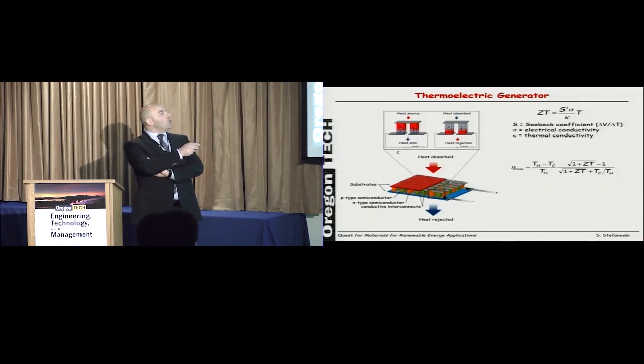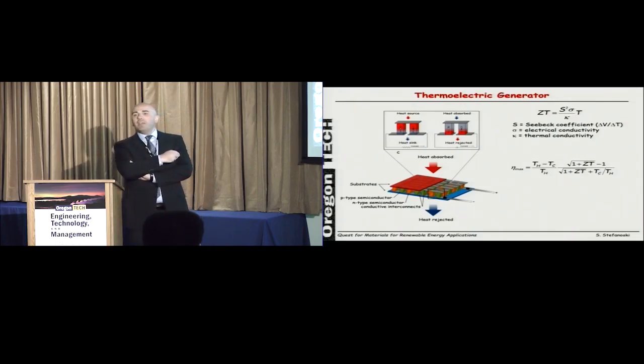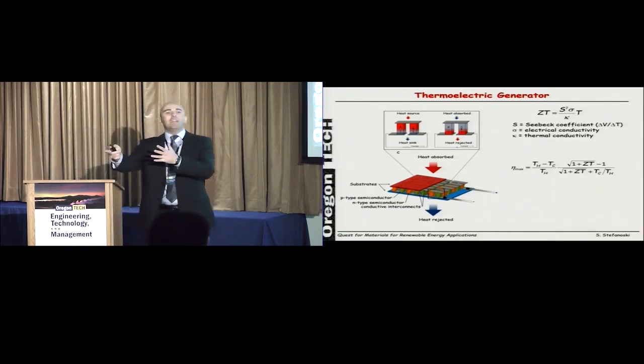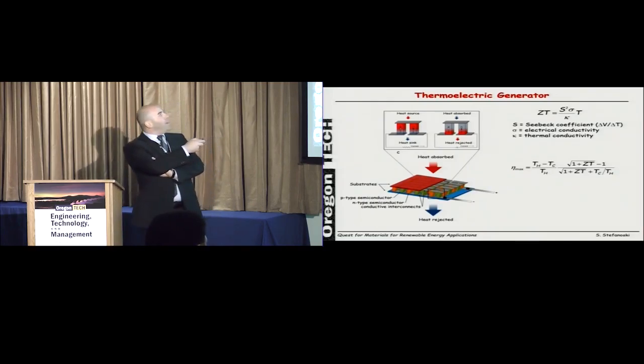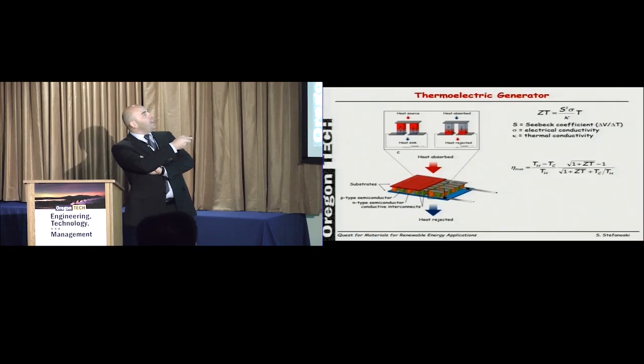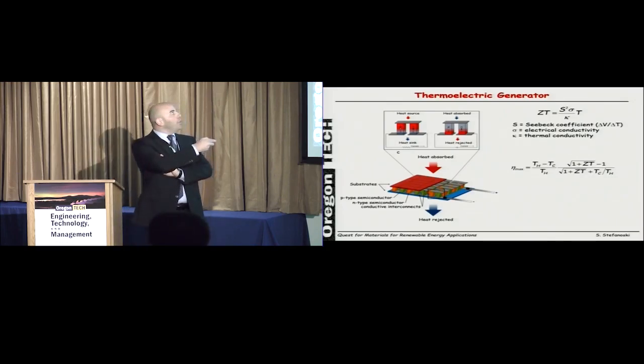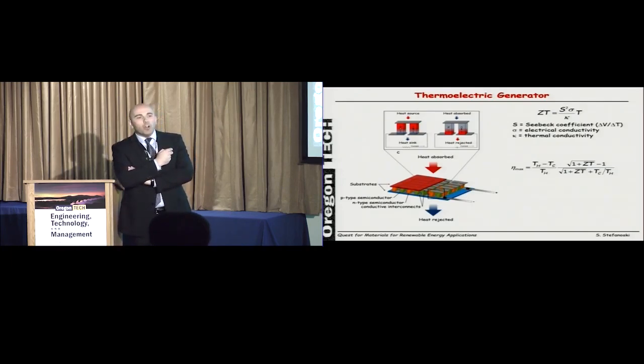Thermoelectric heating or cooling can be done when you apply a heat source on one end. What you have is basically a thermocouple, or a couple of two dissimilar materials, one P, one N, and if we apply heat on one end, the charge carriers, either N or P, are going to try to move away from that heat, and they're going to pile up at the other side, therefore effectively creating a negative charge, for example, on this end, and a deficiency of negative charge on the other end, or in other words, we have creation of an electric field. The thermal gradient across this thermocouple has generated electricity. That's what we call the Seebeck effect.